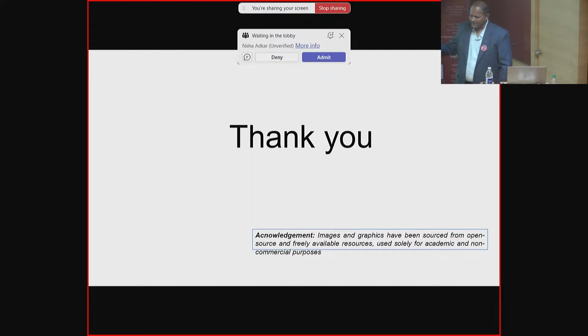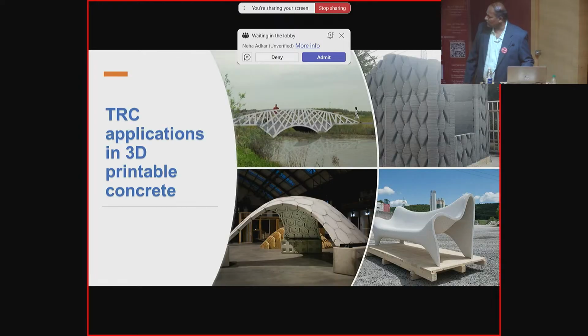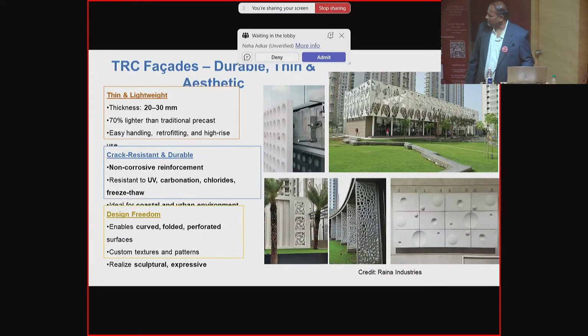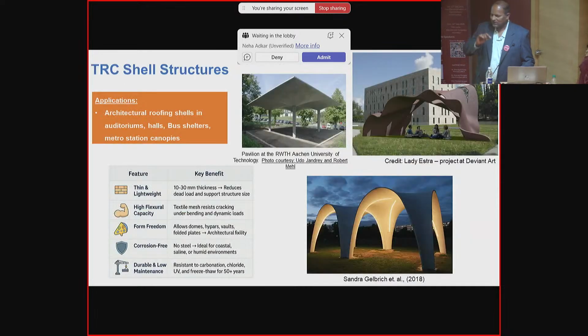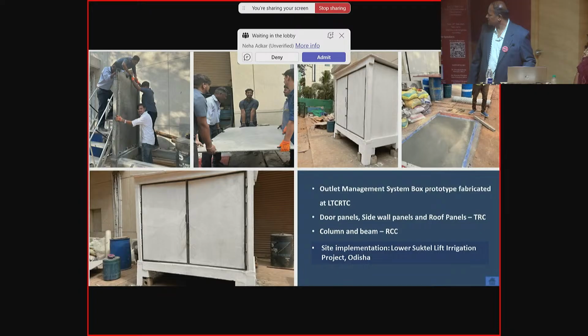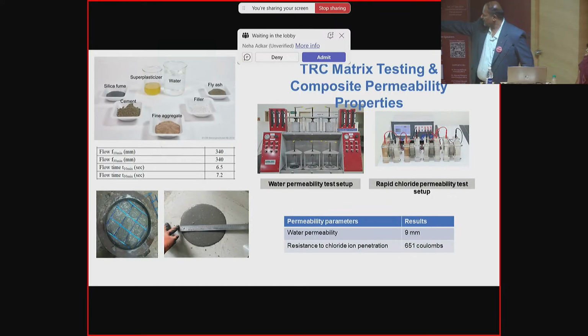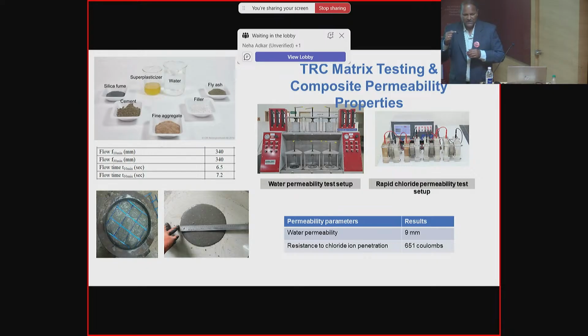Very good. In fact, it is very good candidate for canal lining. We have done the test called water permeability test. I think I have shown one video also. So that water permeability is only just 9 mm. You can see here, permeability parameters. Water permeability is just 9 mm. Actually, the thickness of this element is around 25 mm, in which 9 mm is the penetration depth. This is under the pressure of around 5 bar pressure for 72 hours. Once after 72 hours, we will break it. If we measure the depth of penetration of water, it's only 9 mm. So it can be better utilized.